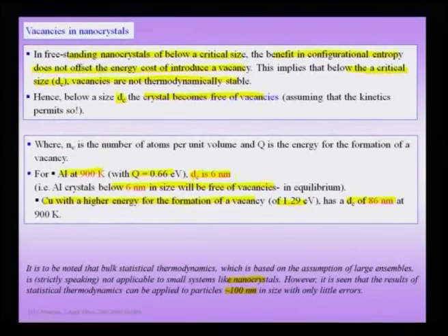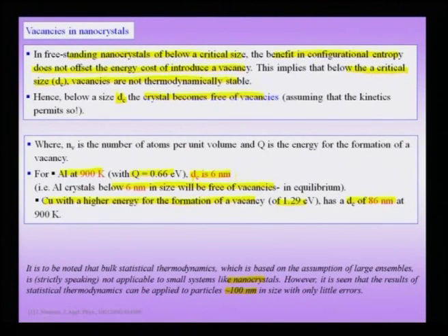An important caveat is that classical bulk thermodynamics — which relies on large ensembles like a mole of atoms — may not be strictly applicable to very small nano crystals. It has been found that bulk statistical thermodynamics applied to even 100 nm crystals gives approximately reliable results, but at very small sizes like 6 nm, classical formulae need to be modified for nano crystals. The key message is that when going down to small scales, the system is expected to become spontaneously free of vacancies — vacancies will not be supported as a stable thermodynamic defect. Similarly, as will be discussed later, dislocations can also become spontaneously absent in nano crystals, though for different reasons than vacancies.